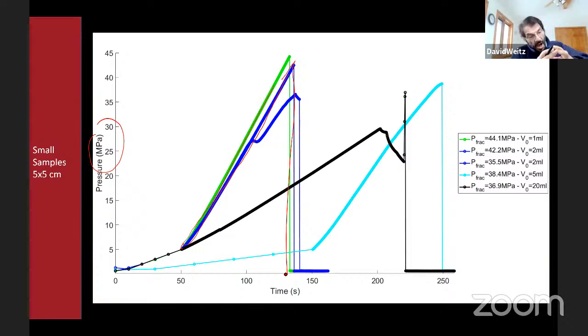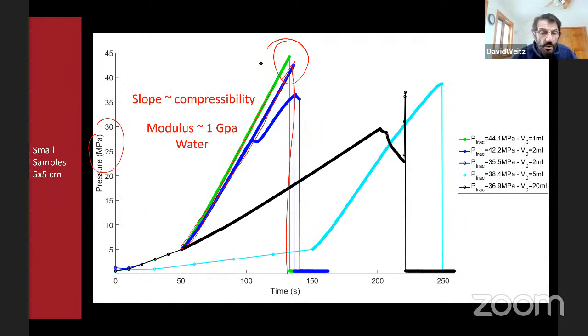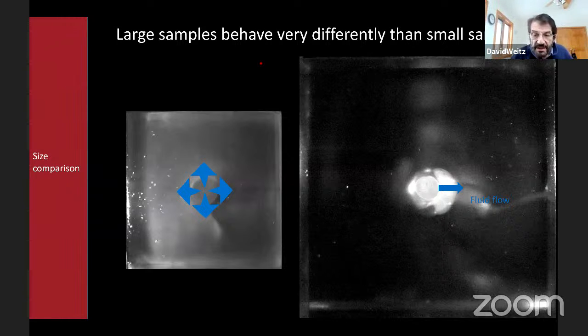You basically are injecting it, and then you're just tearing the whole sample apart. When it cracks, it just completely cracks. It just pulls itself apart. At these pressures, you're actually compressing the water by a significant amount. So the first thing that's going to happen is you're not going to drive more water, but you're going to expand the water as the pressure drops. And it's going to take some time for that expansion to occur, and it's going to take some time for the fluid to follow the crack. It just can't follow the crack. The crack is just getting way ahead of the water. Okay, so what can we do to see something a little bit more indicative of this hydraulic fracking?